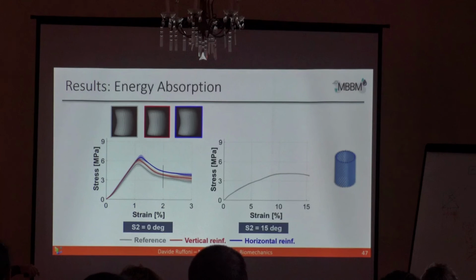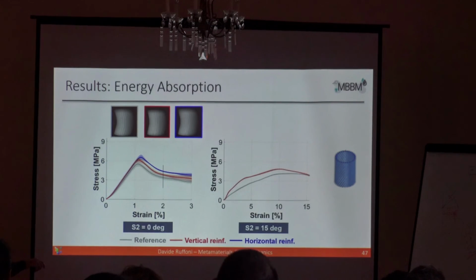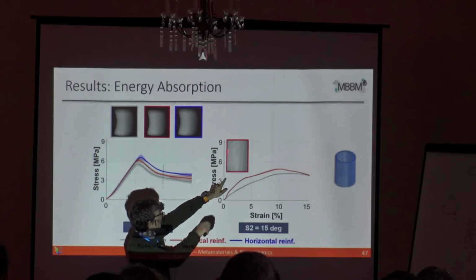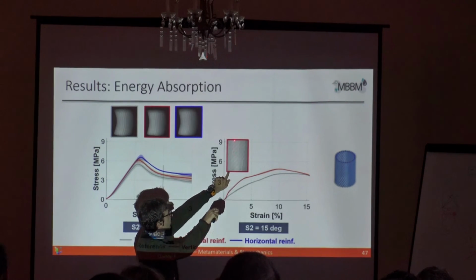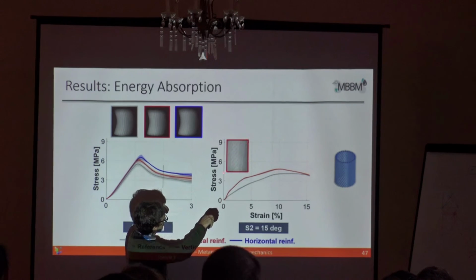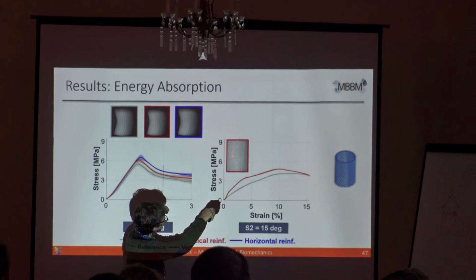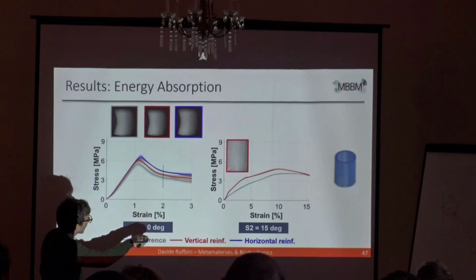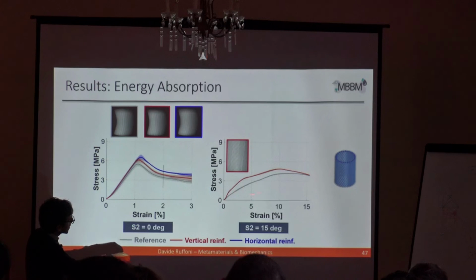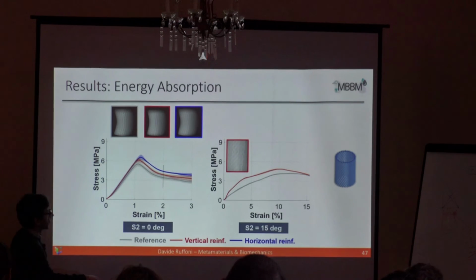Things become completely different if you now introduce some winding angle in the main layer. These are now results for 15 degrees orientation of the main fibers. Now I introduce small vertical reinforcement. Well, it changes a little bit, but you still have this collective buckling of the vertical reinforcement. I'm not sure if you can see here. So these tilted ones are the main fibers, and what you see straight are the small reinforcements that we have inserted, and you see they all buckle collectively, and so the system does not change its overall behavior so much.